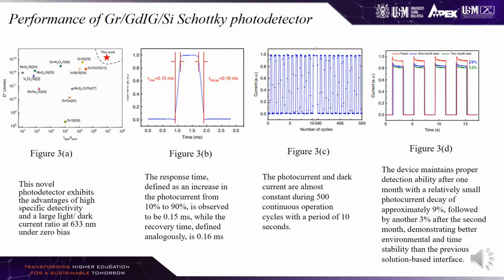Figure 3b shows the response time, defined as an increase in the photocurrent from 10% to 90%, is observed to be 0.15 millisecond, while the recovery time defined analogously is 0.16 millisecond.